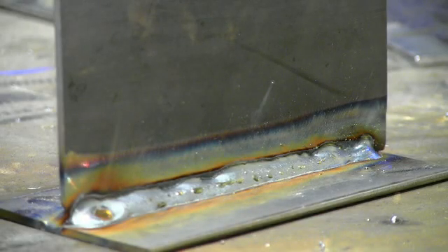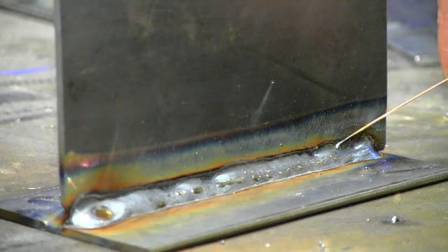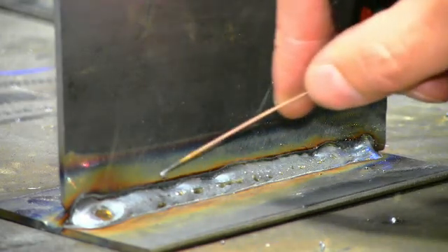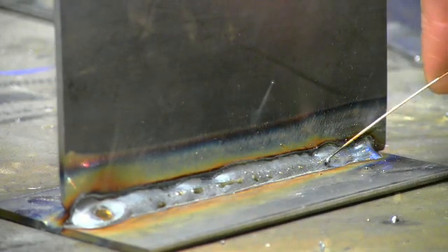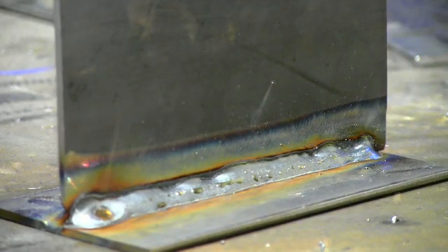So from that welding arc, what you could see was that there was very little spatter. The arc was very quiet. However, controlling the bead shape was very difficult. And you can see up here at the toes of the weld how difficult it was to maintain some consistency, and we have some undercut present. And so we just had way too much voltage for the wire feed speed that we were running.